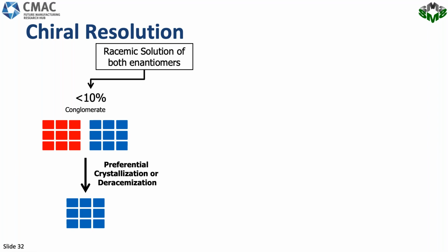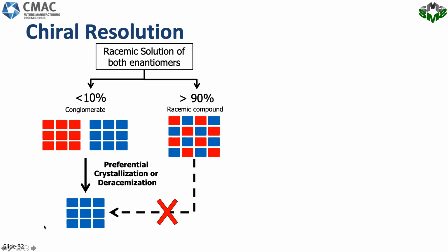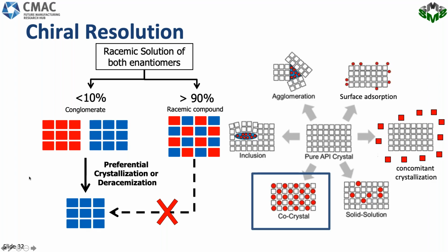Unfortunately, only 10% of the chiral compounds form such conglomerate systems. 90% of these compounds form racemic compounds, and racemic compounds contain both enantiomers, so there's no separation power for these crystals. Actually, this coincides with what I showed as a mechanism at the start, where we form a co-crystal. So here we form a co-crystal of the two enantiomers, and that is very difficult to get rid of, this impurity enantiomer.